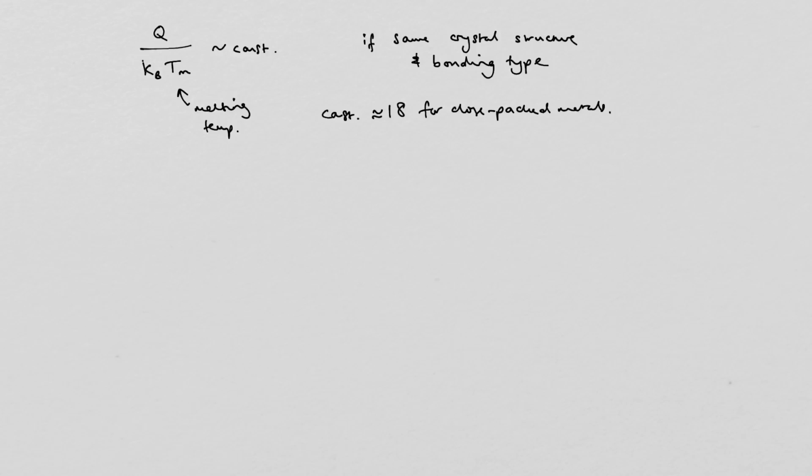Okay. Do you understand why that is? It's more difficult to diffuse upon this strong, and also melting temperature is directly related to the strength of the bond. Exactly. Okay, the things that contribute to Q, vacancy formation energies, migration energies, are directly dependent on the strength of the bonds between atoms, as is the melting temperature. So in other words, it's just a proportionality relationship.